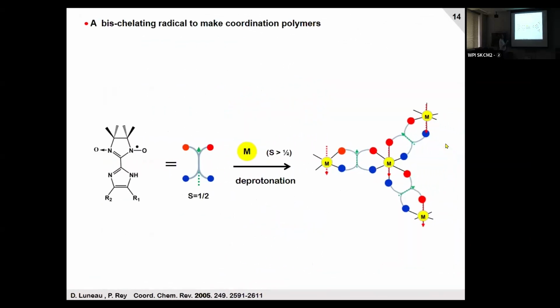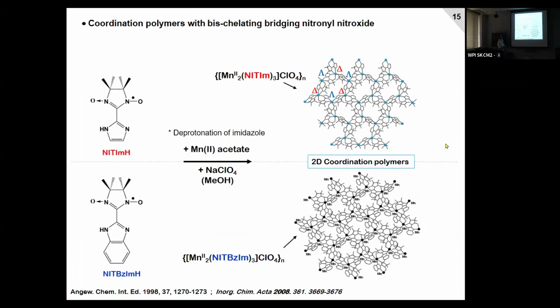So the idea was to use this radical almost like the oxalate, like the magnetic oxalate, in such a way to have an extended network of metal, radical, metal. And it worked quite well. So if we use these radicals, if we use manganese 2 acetate, we use it both as manganese 2 provider, but also because the acetate is a base, we can deprotonate the ligands. And in that case, we get an extended network.